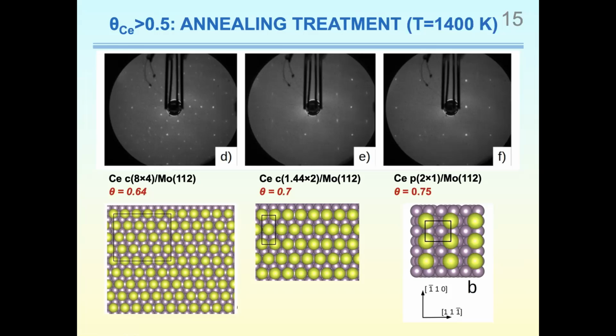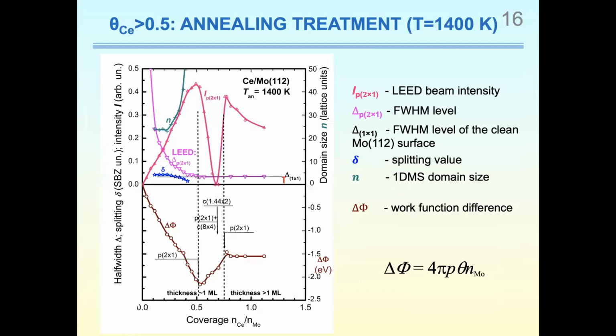Please note that they have not been validated by any kind of simulation, so these are tentative suggestions compatible with LEED patterns. One of them, centered 8x4, has been observed in coexistence with primitive 2x1 in the coverage range from 0.5 to 0.63, indicating the first order transition. You may see that in this range, both structures exist. Another structure, 1.44x2, has been detected as a single phase that undergoes continuous uniaxial compression along the furrows during coverage growth.